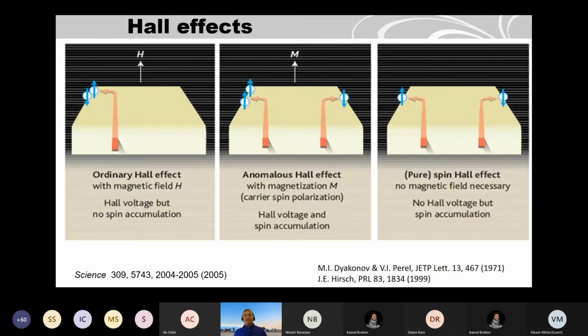Okay, and just in 2004, 2005, the spin Hall effect was first realized in semiconductors. When you have a material, you don't need to apply a magnetic field or have magnetization in the material. But when the material has huge spin orbit coupling, for example platinum, gold, and semiconductors like gallium arsenide, you just pass a current here. You don't apply any magnetic field and there is no internal magnetization in the material, but the electron spins, the up spin will be accumulated on the left, for example, and the down spin will be accumulated on the right. That is the spin orbit scattering.